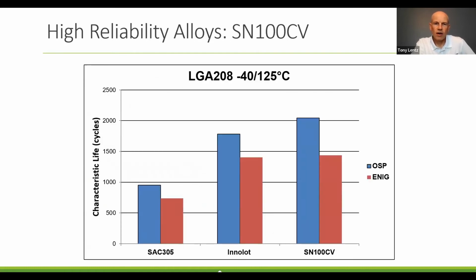Here's some data on an LGA 208 component that went through cycling at -40 to 125 C. We've got SAC305 versus Innolot versus SN100CV in this data. And this was run on both OSP and ENIG surface finishes. So you can see that in this case, SN100CV on the right actually had a longer life than Innolot and SAC305 for this particular component in this test.